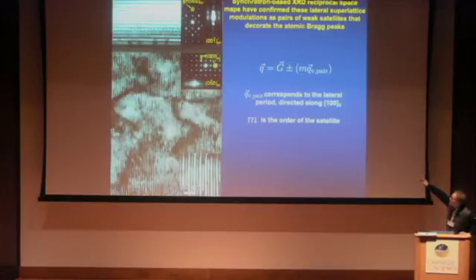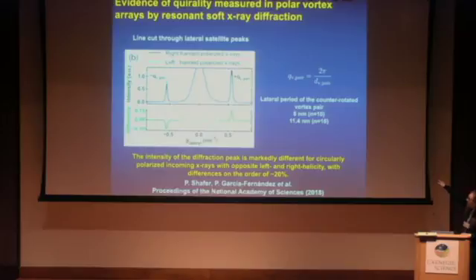So essentially here, what we have is, okay, those are the typical spots obtained from the XRD experiment. And if we look at one of these spots in detail, we can detect the presence of satellites here that are the signature of a superlattice, of a superstructure with the clockwise, counterclockwise vortices. And if we perform here a horizontal cut, and plot the intensity of the diffracted X-rays, we can see two things. First, the appearance of the satellites with lateral periods that match very well with the counter-rotated vortex pairs. But second, that the intensity of the diffraction peaks is markedly different for circularly polarized incoming X-rays with opposite left and right-handed helicity, with differences that may be up to 20%. So this is a clear indication of X-ray circular dichroism, which is the fingerprint for chirality in the system.